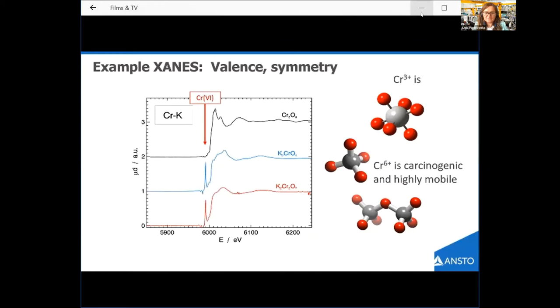But you'll also notice there are two chromium 6+ spectra here, the blue and the red, and they don't look exactly the same. So above the edge, in the high part, there are some differences in oscillations there. And that's because they have a different structure and different local environments, different neighbors.